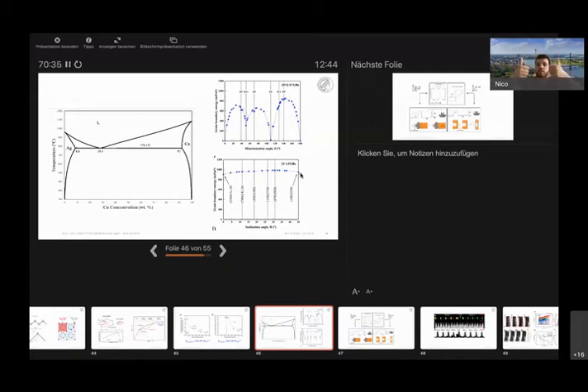So you have both zone axes, or you have the 210 boundary with both grains oriented in 36 degrees. And now you rotate one relative to the other, right? Yeah. And then you record the energies and you get this curve. So you can tell that all the asymmetric boundaries have very similar energies, a little bit higher than the two special boundaries, so to say.